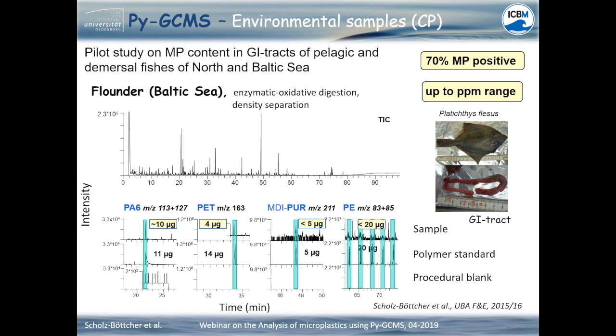Around 70% of the fishes were positive for microplastics in their gastrointestinal tracts, and the microplastic concentration was in ppm range. This example was performed with Curie-point pyrolysis, and therefore the concentrations are at the lowest end of the calibration curve.